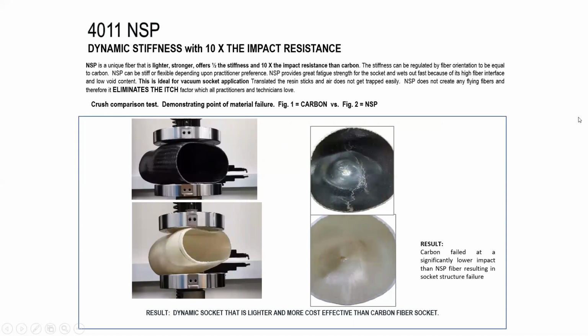Some of the results we got showed that the carbon failed by the fiber cracking. Now, similarly, the NSP that we use did not fail, but the resin crazed. It allowed the material to move. And this is how we were able to determine that the NSP fiber has 10 times the impact resistance, because it did not actually crack.